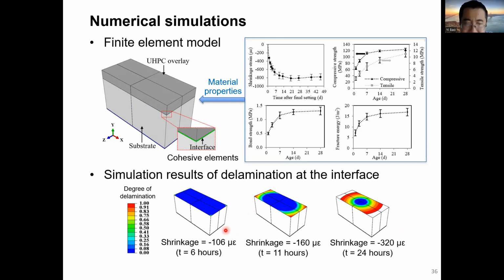So as you can see, at a very early age, well, actually delamination started to happen at 6 hours after the final setting. And then when the shrinkage increased over time, we can see that more delamination happened. This delamination area increased over time, and eventually we could predict the final delamination condition. With this computing technique, we were able to guide the design of ultra-high performance concrete.